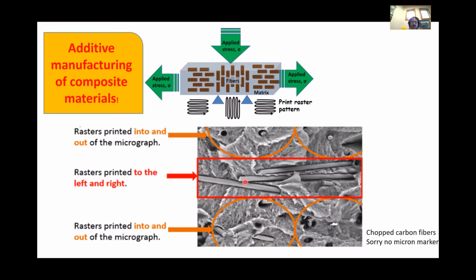And we have this micrograph here of chopped carbon fibers we've thrown into a polymer matrix. And you can see they're coming out here. So this top part, the raster is coming in and out of the screen. And so you can see how the fibers are. And you also see they pulled out. And we'll talk a little bit more about that later. And going this way, they've aligned with the print raster going in this direction. So one layer came in and out of the screen, the other layer went this way, parallel with the screen, and then the other layer again came in and out of the screen. So we had alternating print layers, and you can see it aligned the fibers pretty well.